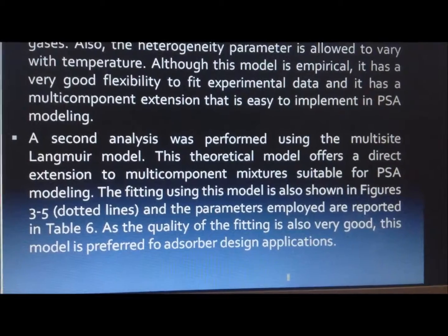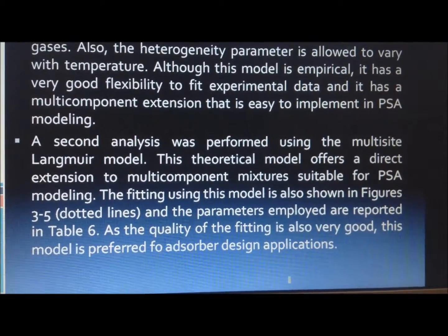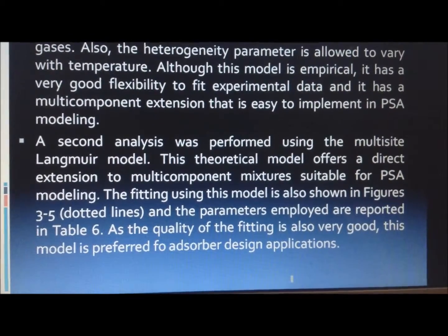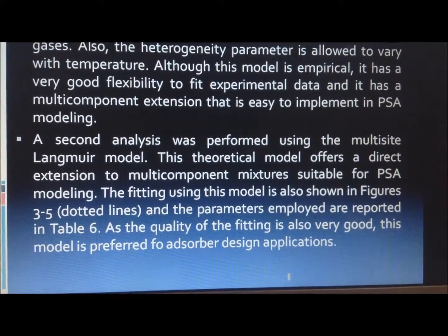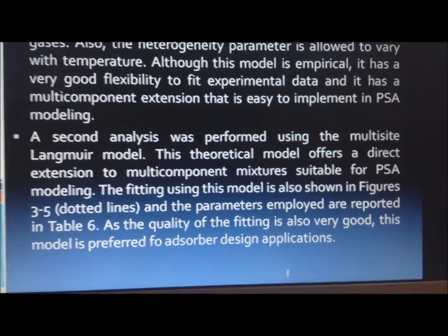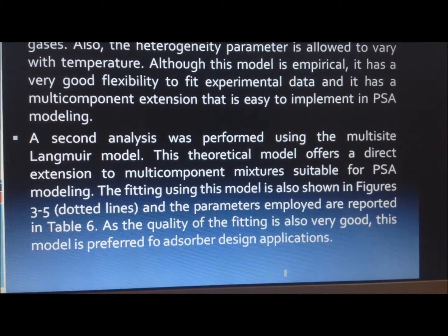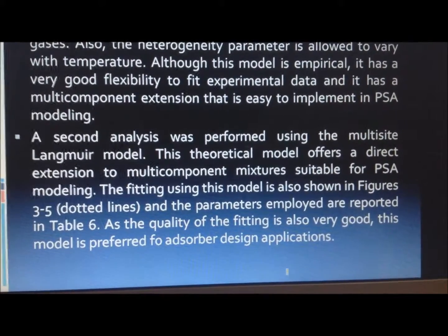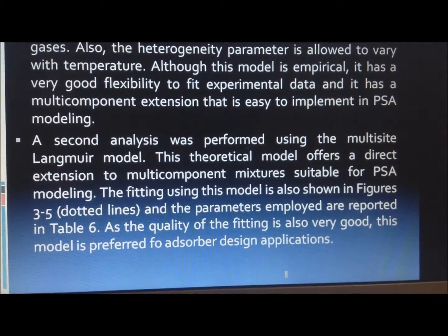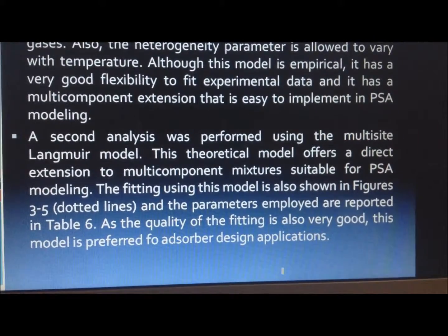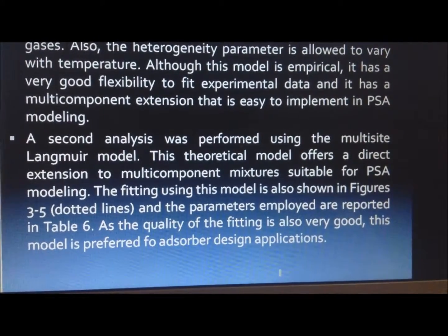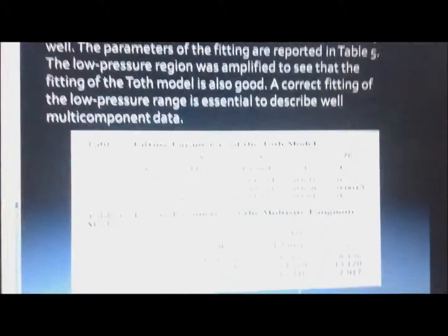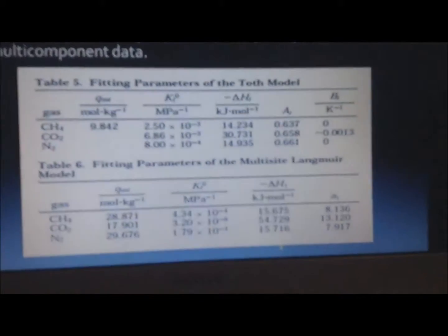A second analysis was performed using the multi-site Langmuir model. These theoretical models offer a direct extension to multi-component mixtures, suitable for PSA modeling. The fitting using this model is also shown in figures 3 to 5. That is represented in dotted lines, and the parameters employed are reported in table 6. As the quality of the fitting is also very good, this model is preferred for adsorber design applications. This is table number 6.